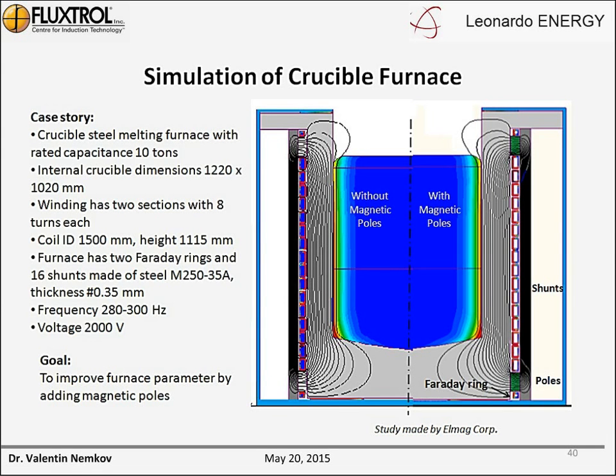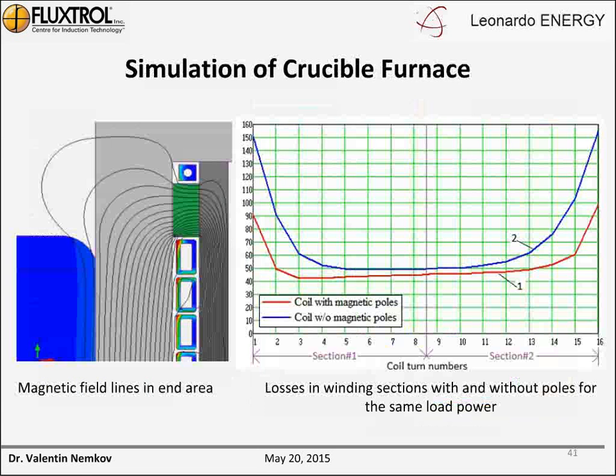The idea is to place an additional magnetic controller in the area where there is some narrow bottleneck for a non-magnetic flow path. So these areas are just above or under the induction coil, because the typical induction furnaces of this type have Faraday rings that protect the frame from heating. What are the results of using these small additional poles? On the left side, you can see this green, it's an additional pole, and the gray part on the right is the stainless steel shunt. The curves show that introduction of these poles significantly reduces losses in the coil turns.